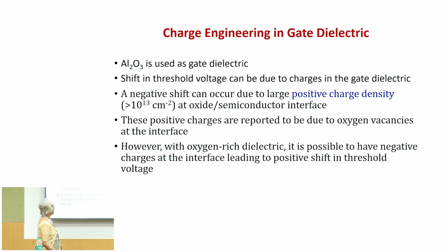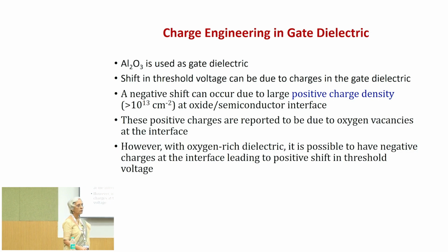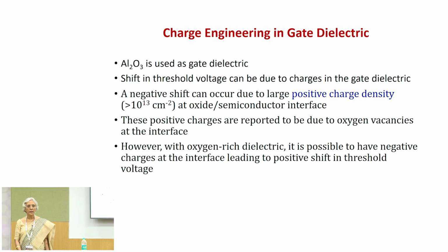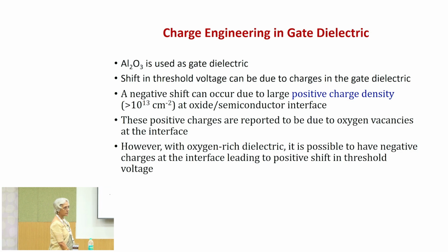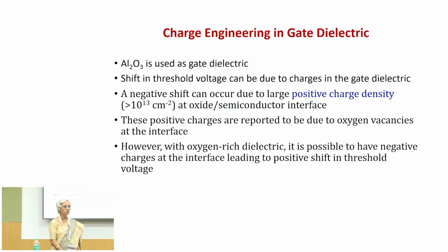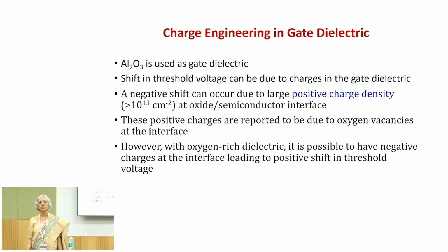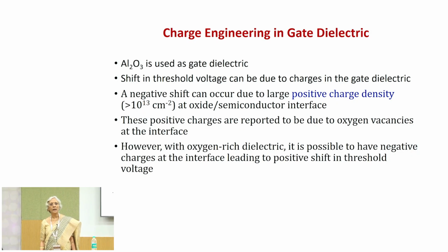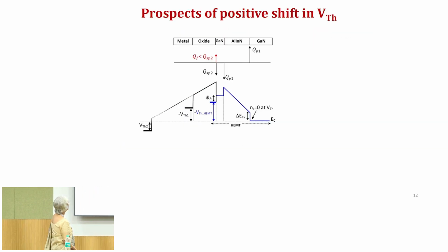Now, when we do a composition analysis, we find that usually people have reported a negative shift in the threshold voltage for MISHEMT, and that is because of the oxygen vacancies at the interface. That is, at the interface the aluminum oxide is not really Al2O3, it has oxygen vacancies, and therefore, it is aluminum rich aluminum oxide, and that gives rise to a lot of positive charges. However, if you can have a process in which you are having an oxygen rich aluminum oxide, then it is possible that you can have more negative charges introduced at the interface, and therefore, the shift in the threshold voltage can be positive. So, this is what we tried, and we were successful to some extent.